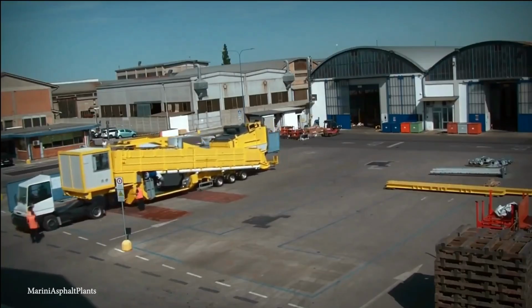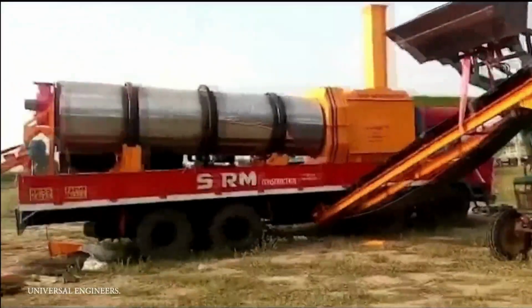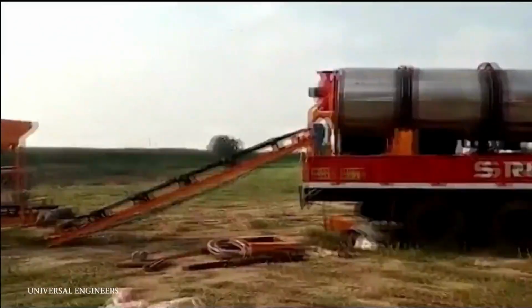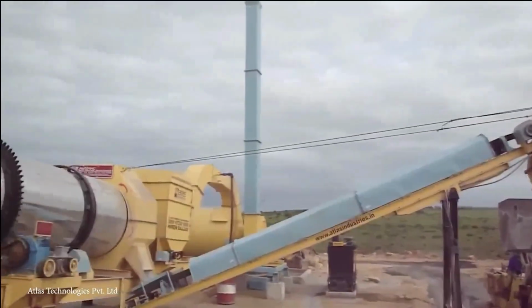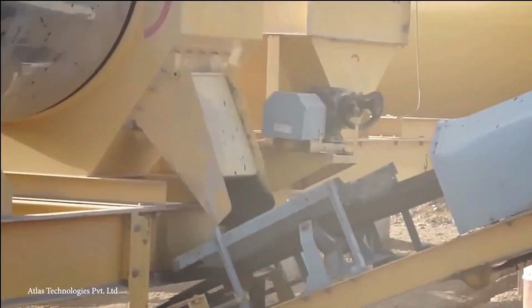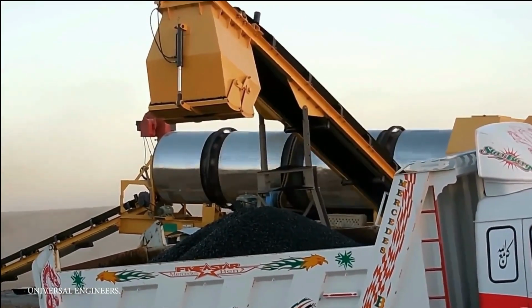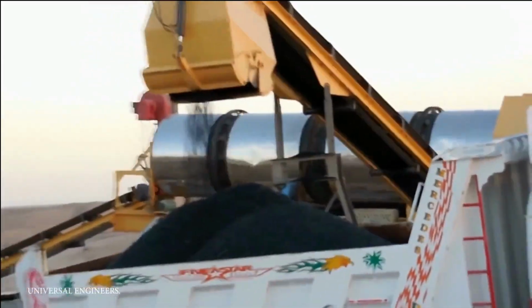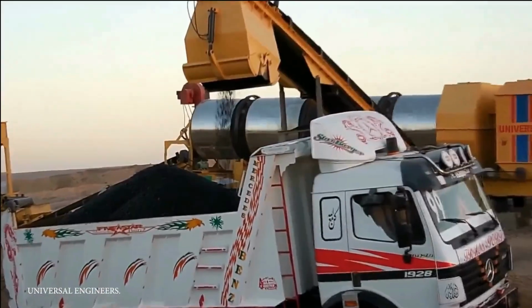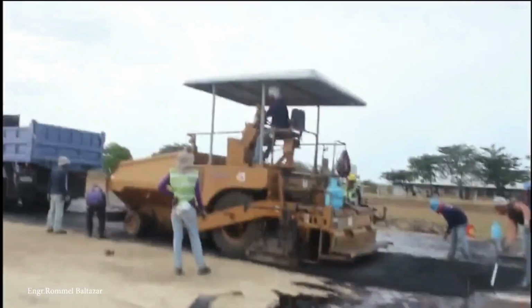These machines are quite complicated, but as long as there's enough material available, they can be far more effective at providing the required amount of fresh asphalt to a project. The asphalt itself is made up of aggregate, sand and a type of filler, which is normally stone dust. These ingredients are carefully added in the correct proportions to the main drum that spins around to ensure they're combined properly, and slowly heats the mixture to a temperature between 212 and 392 degrees Fahrenheit. When it's ready, the sludge-like asphalt is then ready to be deposited directly onto the new road, and other machines that are responsible for spreading and flattening it can immediately get to work.